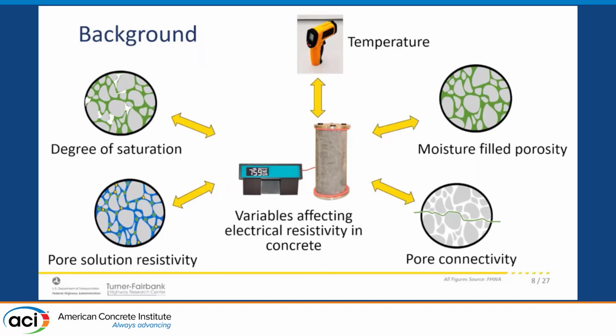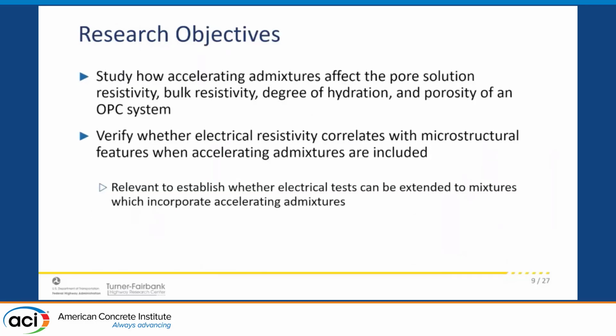So resistivity is not only affected by the pore solution properties. We have all these other factors that play a role in affecting the measurement of resistivity - temperature, degree of saturation, the pore solution. But what we're really interested in is looking at the porosity and the connectivity, because those are the two factors that drive our transport properties.